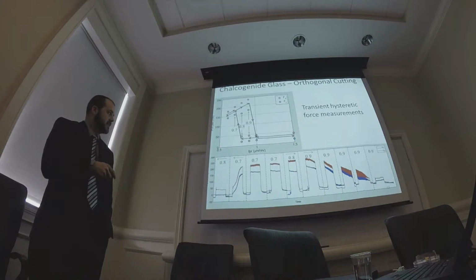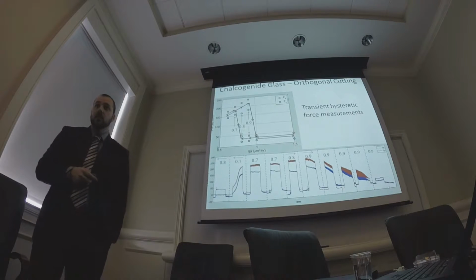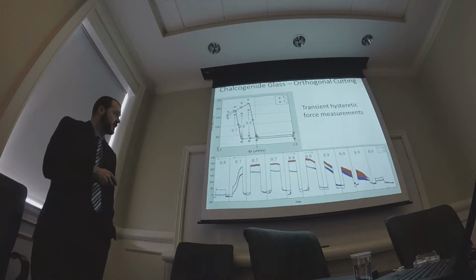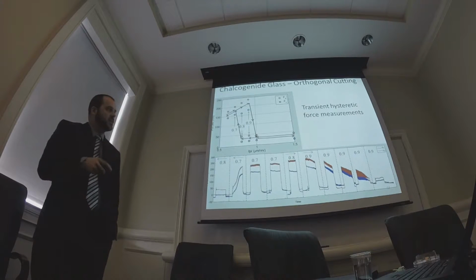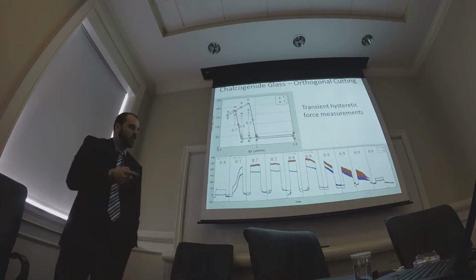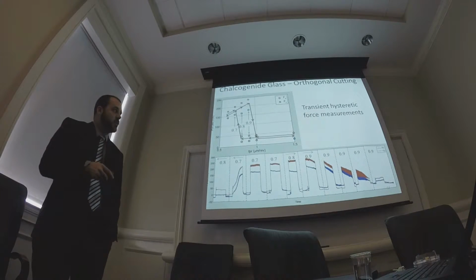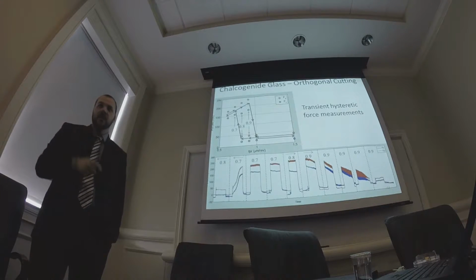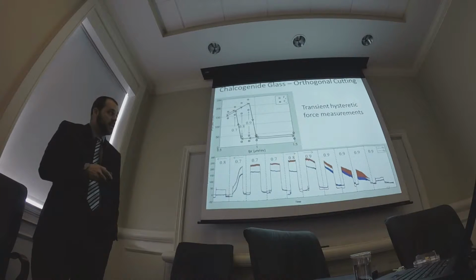And then I step back to 700, and this one takes about 80 revolutions, so it took almost 3 times longer than the last one I showed to get up to this force here. And then it remains there. I work my way back. And then this was a little ways into the testing, so we believed that the tool edge was wearing on a nanometer level, and that's why at 900 for this test we started to drop the force down to a steady state that we would expect to see down here.